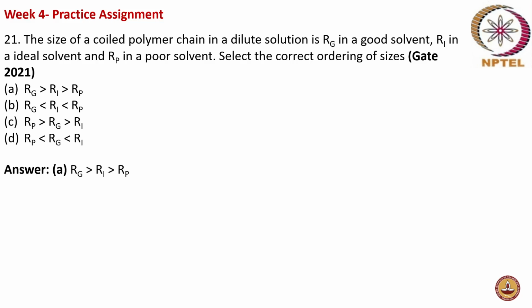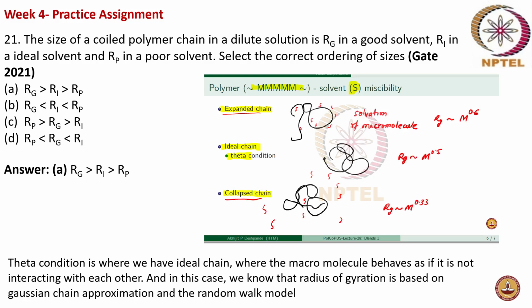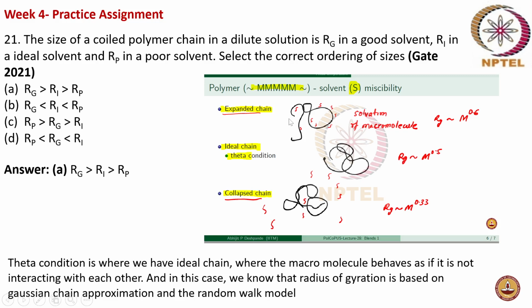It is actually Rg, the radius of gyration in the good solvent will be higher than that of the ideal solvent, which will be greater than that of poor solvent. It's because in a good solvent, you will have more polymer and solvent interaction. The chain will be in a more expanded conformation. That means your radius of gyration will be higher, and it is related to your molecular weight to the power of 0.6.